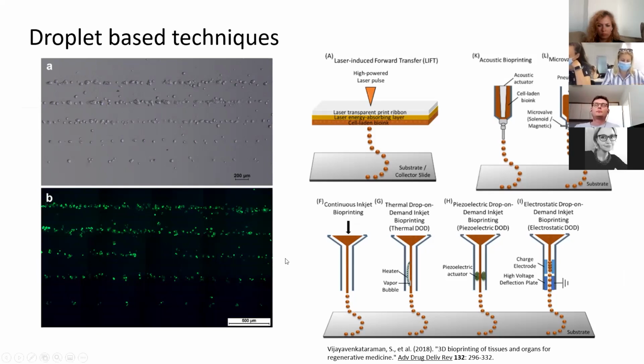There are different methods of driving the material through nozzles, like inkjet printing or piezoelectric printing. But there are also laser-based techniques that are used to make droplets. An example of that would be laser-induced forward transfer, where you focus pulses of a laser on a wet surface with the bio-ink, and then you locally heat up the surface, which accelerates droplets of the bio-ink away from the membrane and towards a target surface.